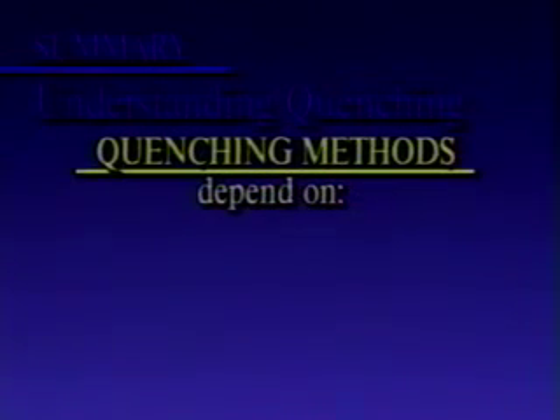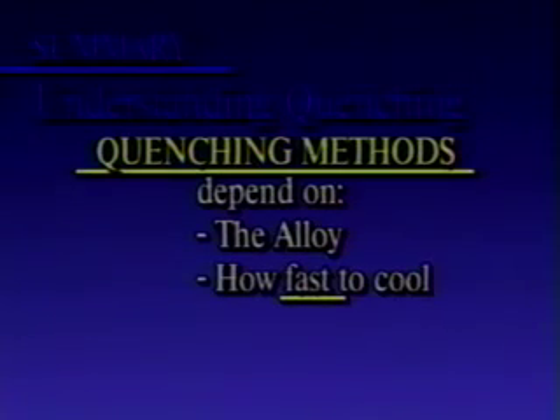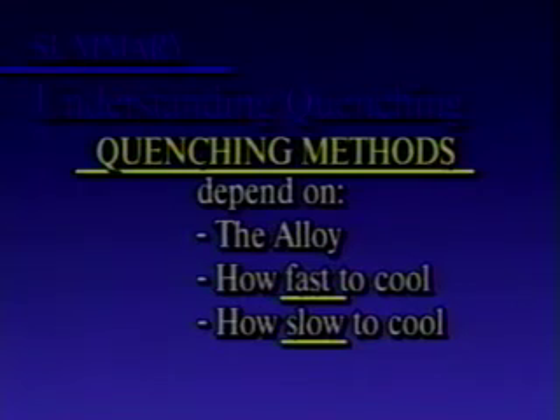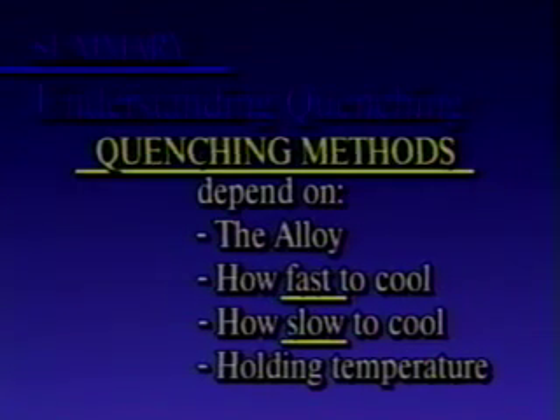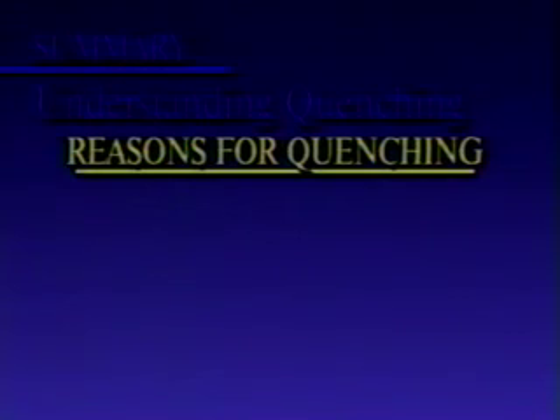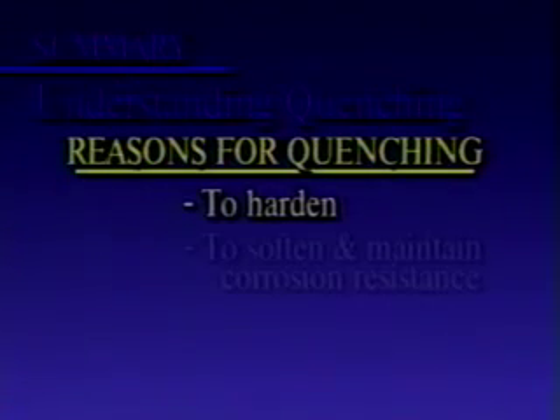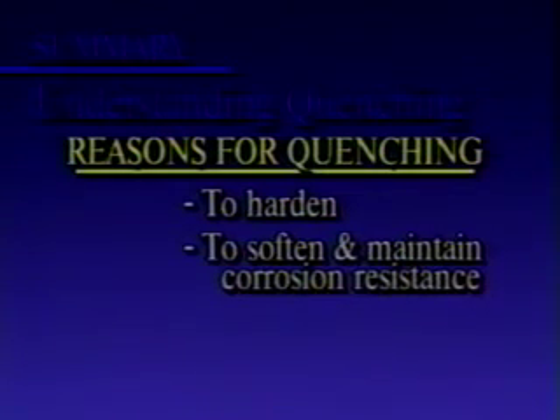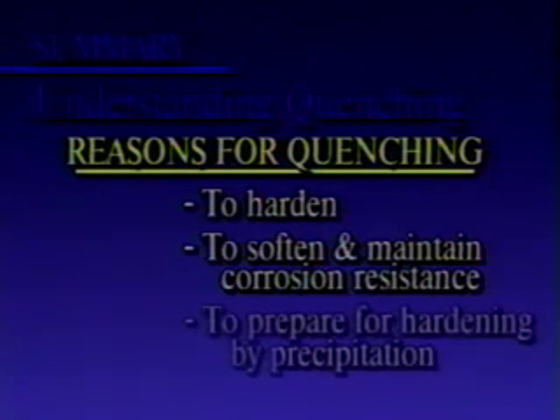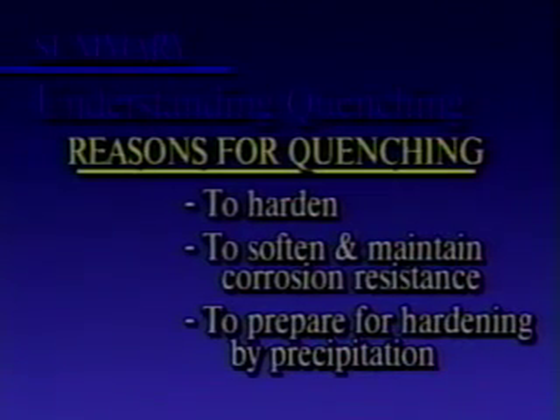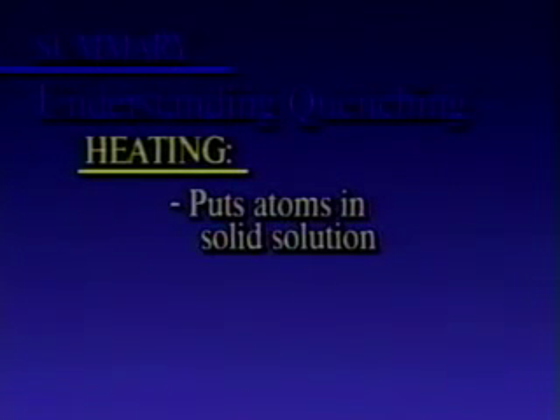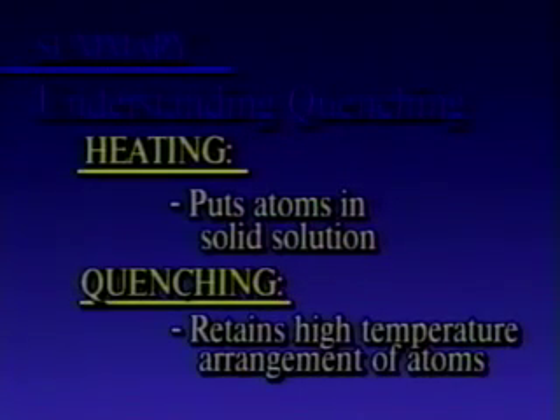Quenching methods vary depending on the alloy, how fast the alloy is to be cooled, how slowly it must be cooled, and the temperature at which it is held before cooling to room temperature. A metal or alloy is quenched for one of 3 basic reasons. Certain steels are hardened by quenching. Austenitic stainless steels are softened by quenching to maintain their resistance to corrosion. Non-ferrous alloys are solutioned, then quenched to prepare them for precipitation hardening. Heating an alloy to high temperature puts all the atoms in a solid solution, that is, a single crystalline structure. Quenching rapidly retains the atoms in the arrangement that exists at the high temperature.